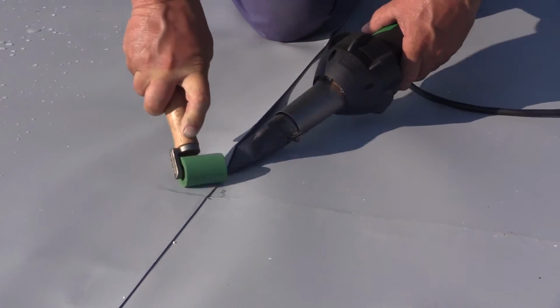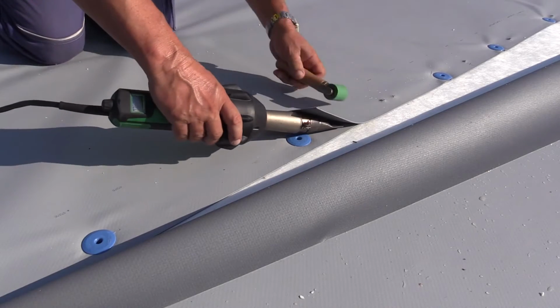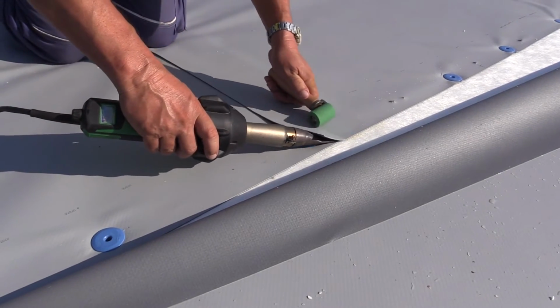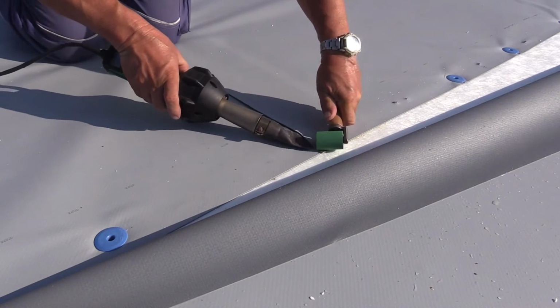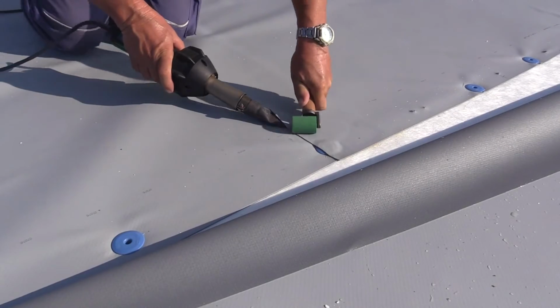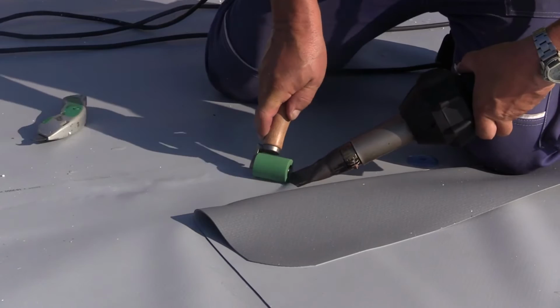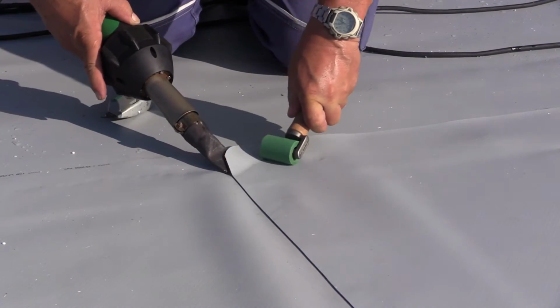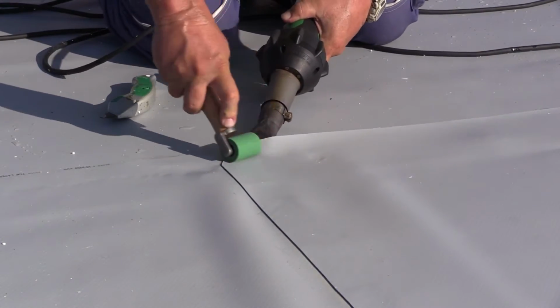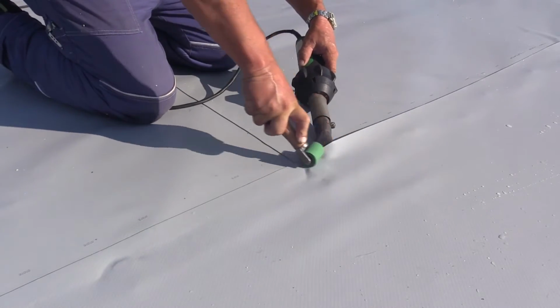The welding tip is directed between both welded surfaces. These must be clean, free of dust, mineral wool fibres, water, snow or ice. The down pressure is achieved by the roller, which moves diagonally to the weld axis. For T-joints, it is necessary to increase down pressure by roller edge. Dirt captured on the nozzle must be removed continuously by a steel brush.